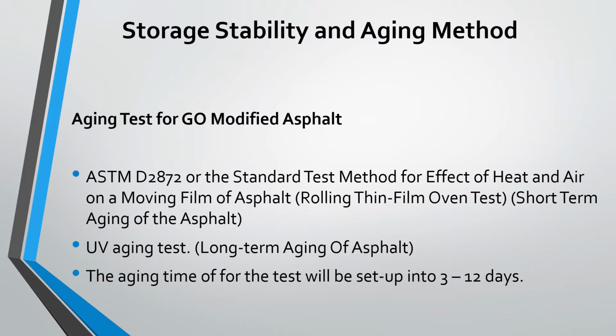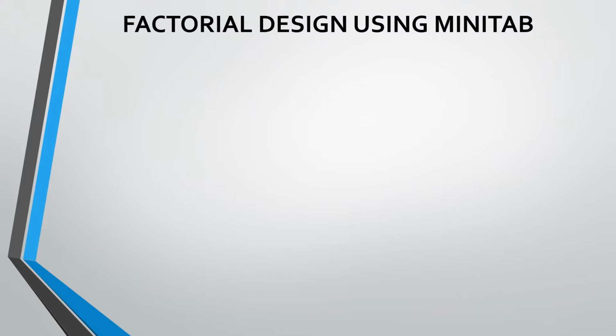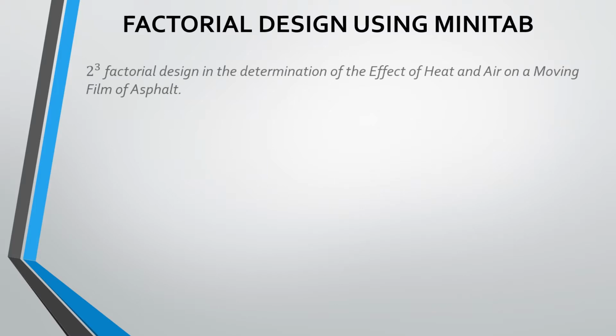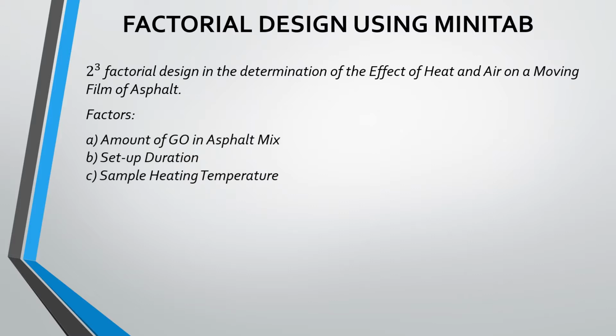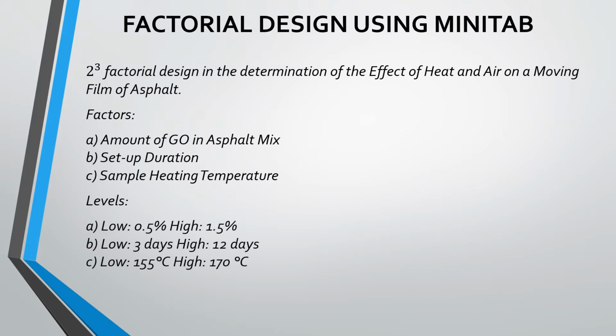In order for us to have a simpler experimentation, factorial design will be used in the study. A 2 to the third factorial design in the determination of the effect of heat and air on a moving film of asphalt will be utilized. We are considering three factors, which are the amount of GO in the asphalt mix, the setup duration, and the sample heating temperature. We will set the levels into two, namely for the GO asphalt mix, 0.5 for the low and 1.5 for the high.